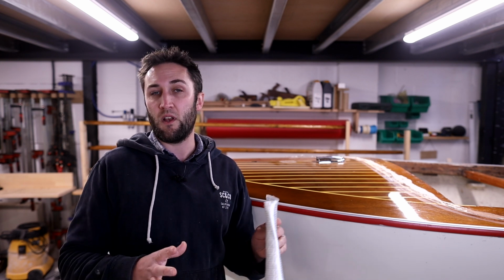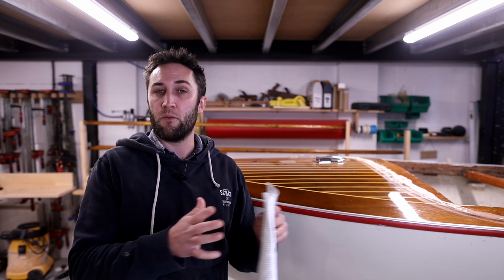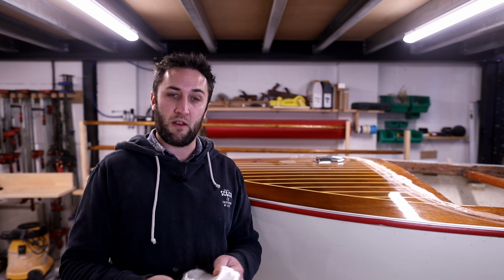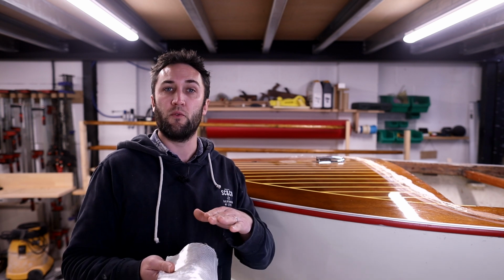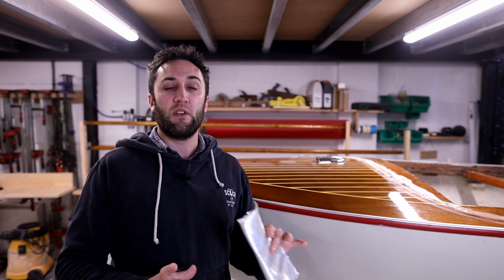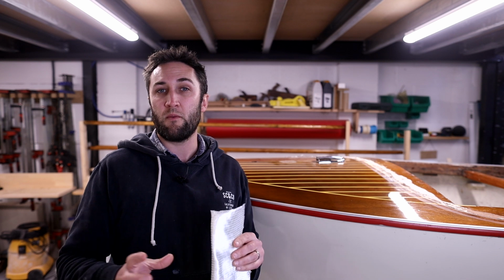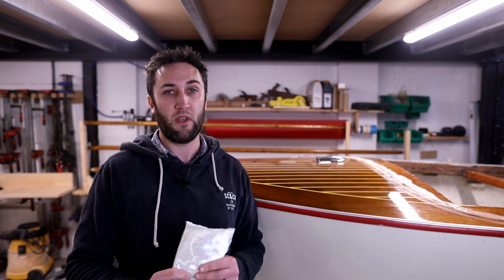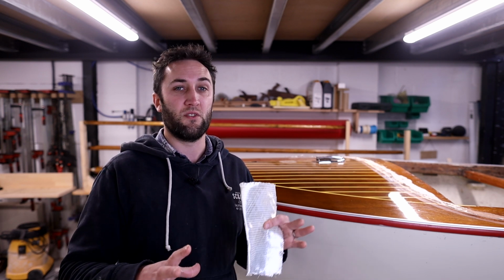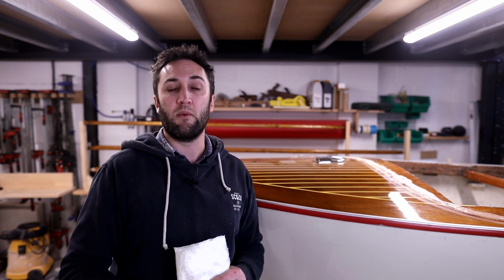We're doing 2 layers of glass on the bottom of this boat. So by the time we multiply that up, we get to 1.8 kilograms per square metre weight that we're adding to the boat. So that's 2 layers of 450 for the glass and 2 layers of 450 for the resin to wet the same section out. If we times that by approximately the total square meterage of the boat, which is around about 6.8 square meters for the bottom of the hull, and the small section up the sides that we're doing, that takes us to around 12.24 kilograms, plus maybe a little bit extra because those are just rough numbers and we may be a little bit heavier on the resin or cloth in various different places.